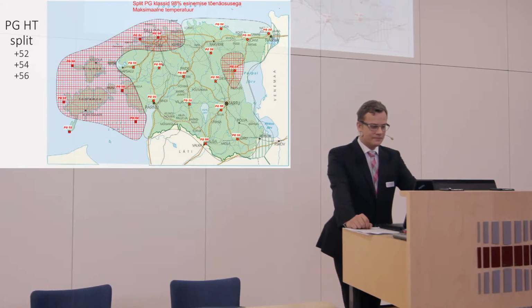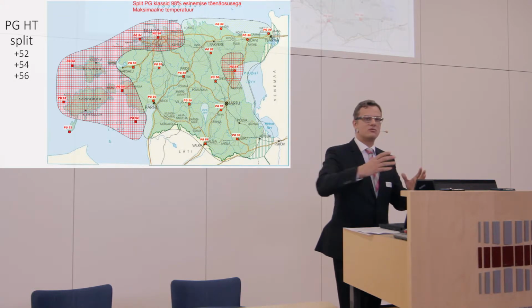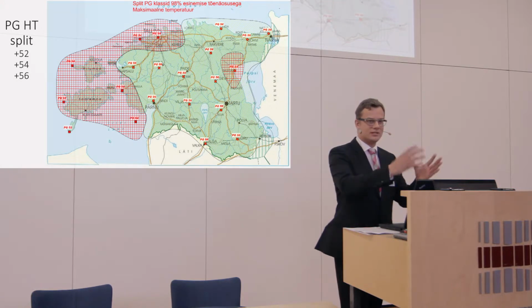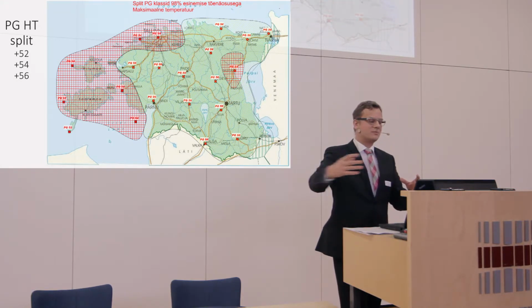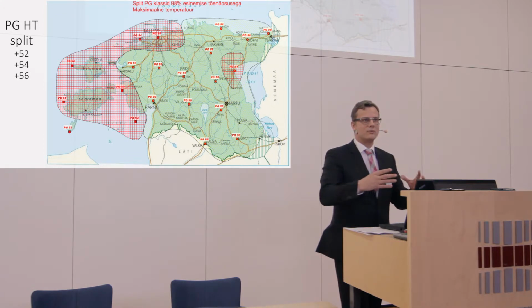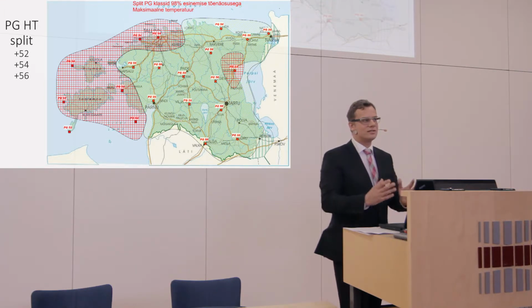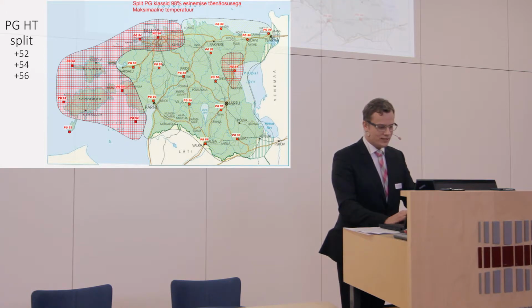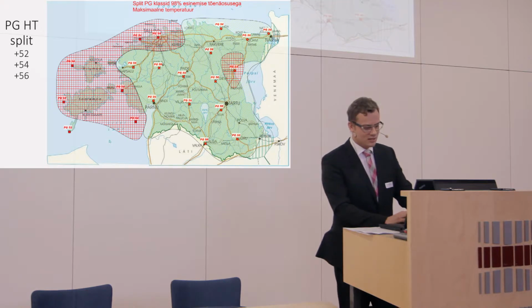Then we made PG grading for preparing PG grade for a bitumen. I'm going to present you PG split grade. In the conventional PG, you have 6-degree differences, so when you start at 50 degrees, then you jump to 56. But now we have split it into 2 degrees to have more information about what is happening in Estonia in reality, and about our bitumen, what are the split grades for them. So as you can see, when we take a split grade, you could have plus 52, plus 54, and plus 56 degrees in Estonia.